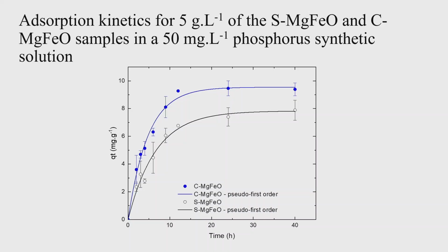And it basically means that the amount of sample adsorbed does not depend on the number of adsorption sites. When this model works, it works because in one point of the equation, you put infinite adsorption sites. The number of adsorption sites is so big that their derivative, the reduction in the number of the adsorption sites, does not count. Okay? The phosphorus atoms that are bound depend only on the number of phosphorus atoms that are in the liquid.